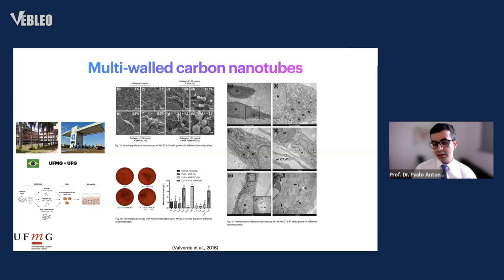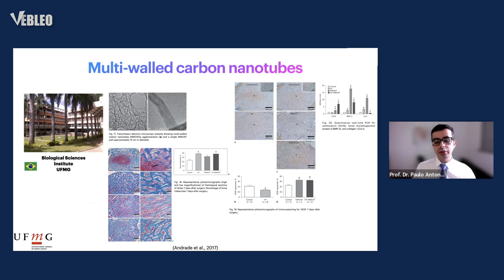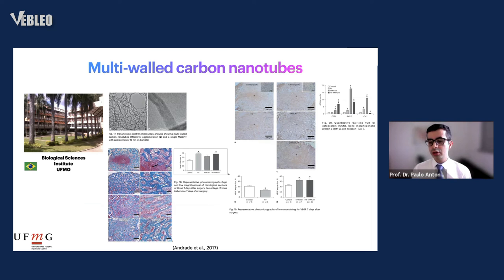In figure 15, we see that cells can phagocytose nanotubes into the cytoplasm. In 2017, we worked with a different model — a bone defect created in the tibia of rats. Working with multi-walled carbon nanotubes, we can see that these materials in this new type of bone defect experimental model also enhanced bone repair regeneration, enhancing the expression of VEGF, osteocalcin, and BMP-2, as assessed by immunohistochemistry.